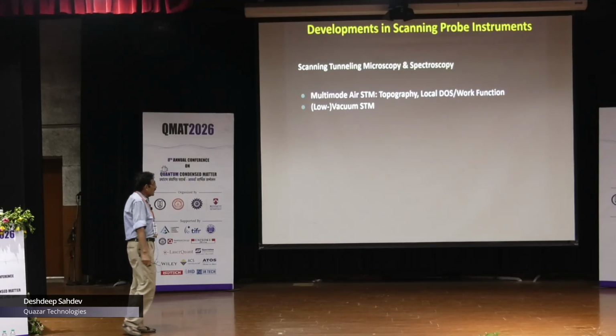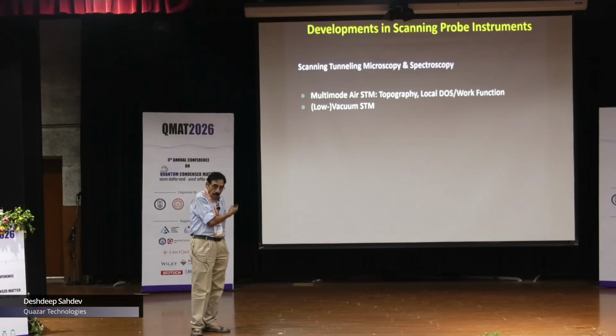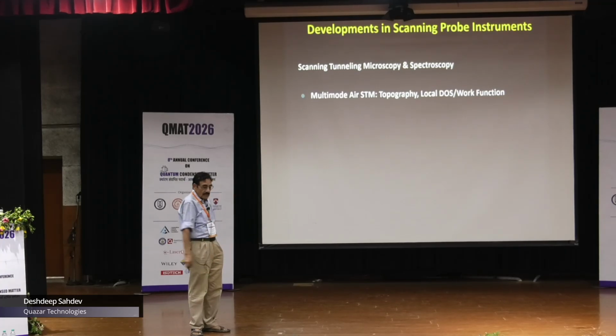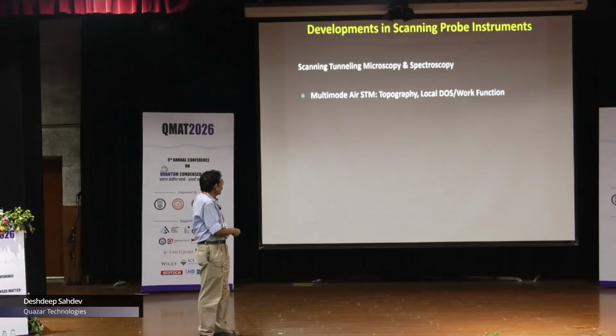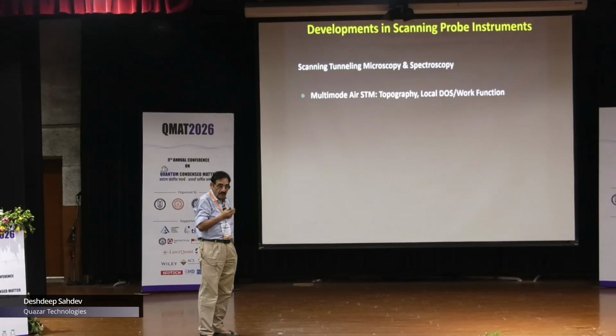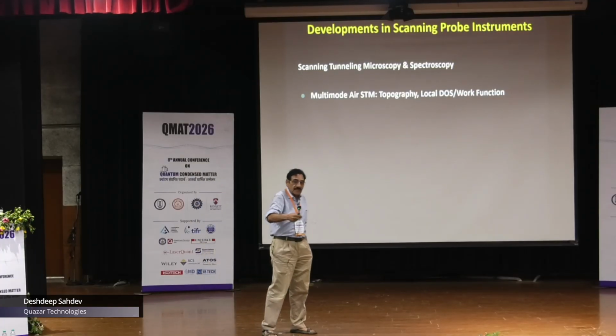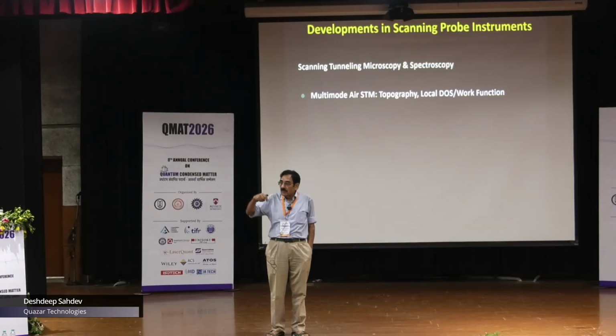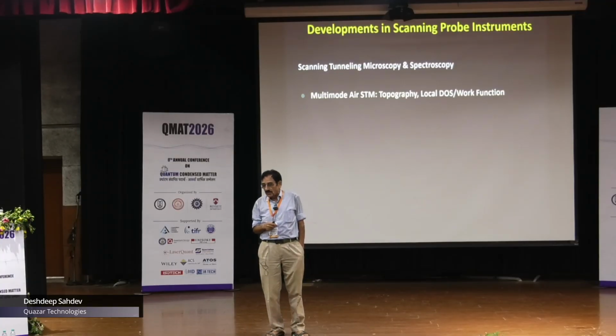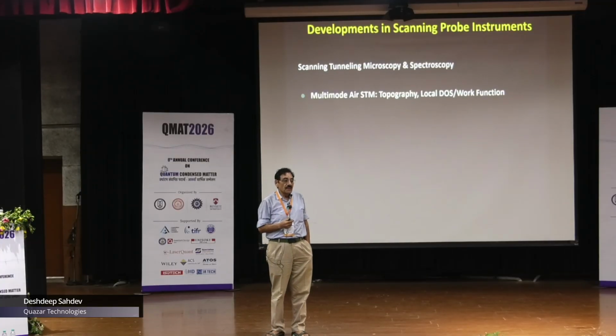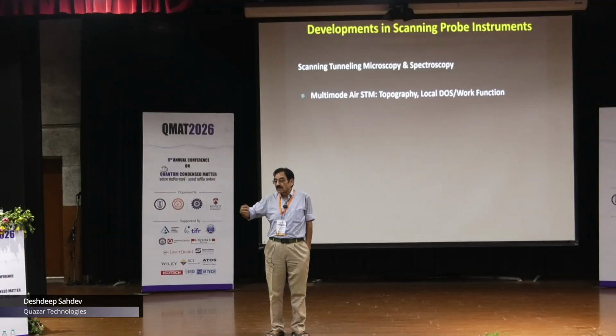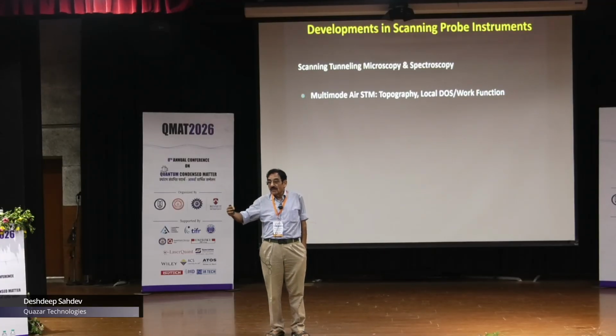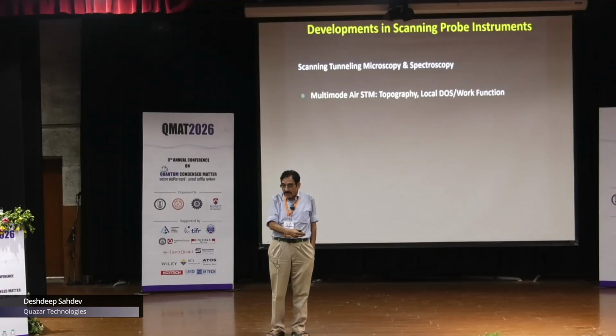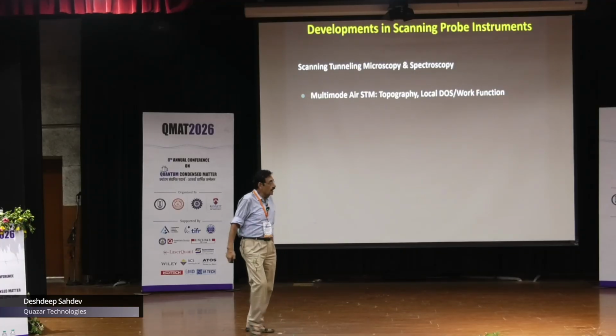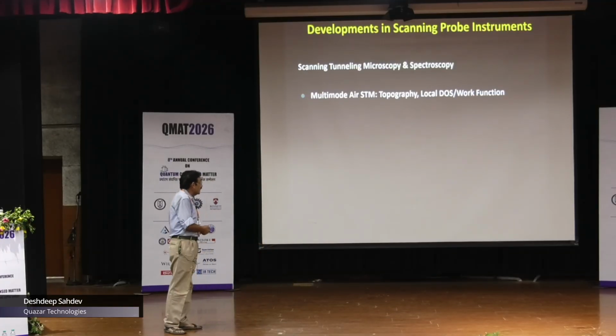We went on to putting in... It was just topography, but there was also local density of states, and then local barrier height, which is the local work function. And we resolved all of these with not only atomic but subatomic resolution. So what we're talking about is we walk over an atom in 25 steps. So the resolution is 1/25th the size of the atom. All right, so the atom is already a big object.